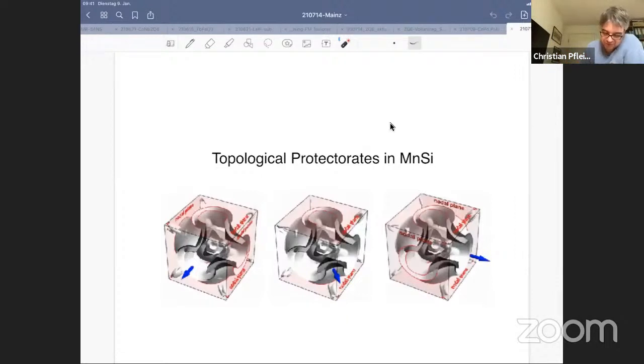But the story is basically, the nodal planes are shown in pink shading. The magnetization is shown in blue. The magnetization follows an applied magnetic field. So I apply the field in this way, I have basically spin split from the surface, I have the nodal planes around here, and I have no nodal planes on the front and the back surface. And if I rotate the field, then I destroy the nodal plane on this side, and there's no nodal plane here, and so forth.